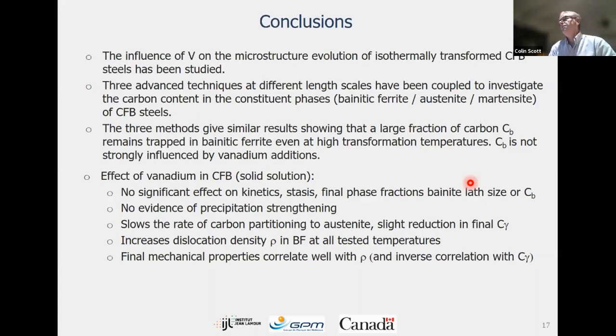There's a large fraction of bainitic ferrite with supersaturated carbon contents, even at high transformation temperatures and at these low carbon nominal steels. The carbon content doesn't seem to be strongly influenced by the vanadium addition, which is maybe surprising considering how strong a carbide former vanadium is, but we don't see it. The effect of vanadium in carbide-free bainite, well, you get an overall strengthening effect, but it's not anything to do with the kinetics, final phase fractions, bainitic lath size, or even bainitic carbon content.